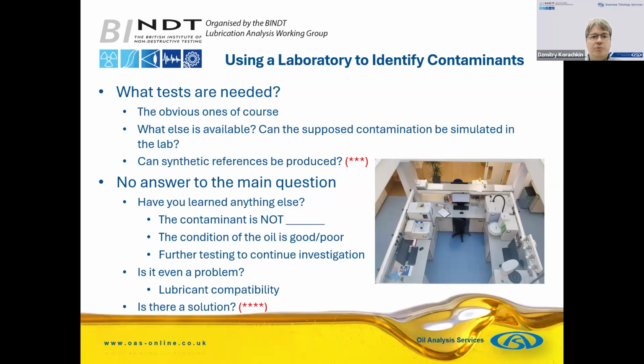Sometimes the lab may be able to prepare a sort of synthetic reference, simulate the contamination. So if you think there's so much of this product getting into this product, if you supply those neat products together, we can mix them and then compare with the unknown sample, and see, is this similar to that mixture? In some situations it's not always possible to fully understand what the contaminant is, you may, however, be able to eliminate a lot of other things and understand that the contaminant is not this. It's not this lubricant, it's not this grease, it's not detergent fluid.